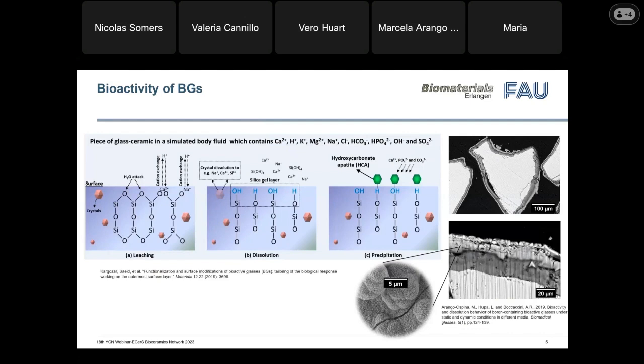What happens is at the beginning, when it gets in contact with body fluids, a series of reactions start. First, the breakage of the silica network, then the formation of silanol on the surface, followed by the formation of the silica-rich layer. And then we have the migration of calcium and phosphorus from the solution, which forms the precipitation of an apatite-like layer, which later on crystallizes to hydroxycarbonate apatite. In the pictures on the right, you can nicely see the silica-rich layer and also the apatite layer on top.